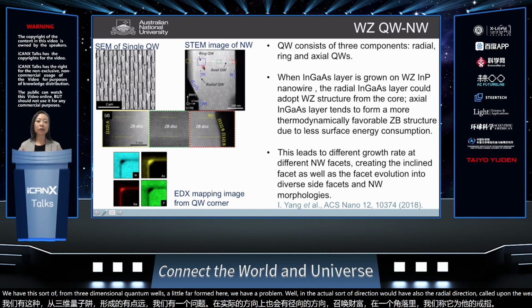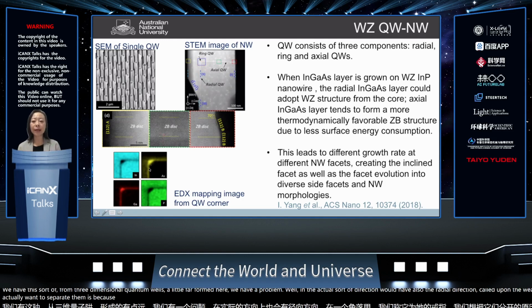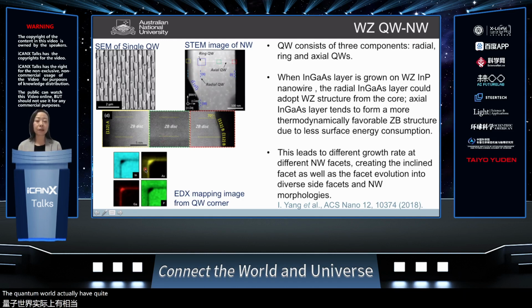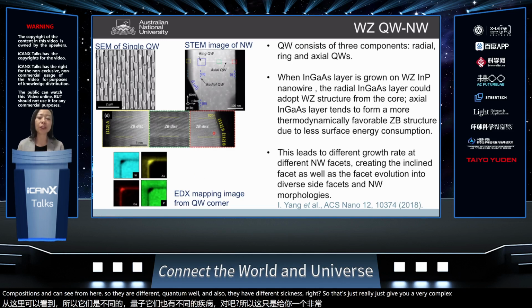The reason we want to separate them is because if you look at the EDX mapping, the quantum wells have quite different compositions, and you can see from here. So they are different quantum wells, and they also have different thickness, right? So that gives you a very complex structure. And of course, we did a very detailed TEM analysis. What we found is that